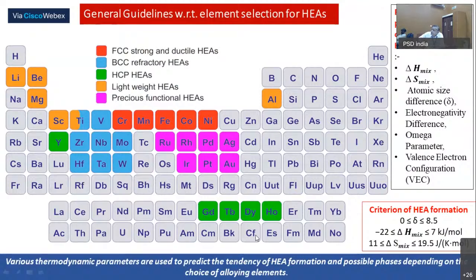For example, we know aluminium shows an FCC structure. So if you add aluminium, it will go into high entropy alloys with an FCC based structure, but it's a lightweight element, very low density, close to 2 gram per cc. So if I add titanium, aluminium, magnesium, lithium, beryllium, definitely I will get a very lightweight high entropy alloy, which is an FCC structure. If you want an HCP structure, look for elements which have an HCP structure.